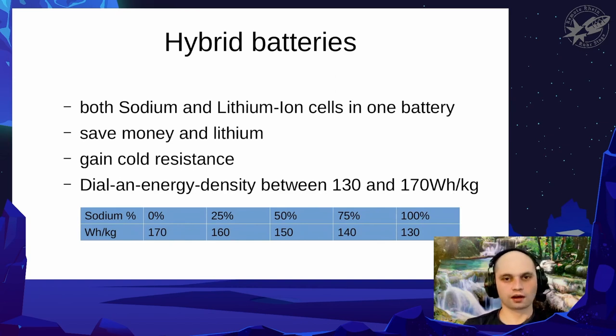And in terms of energy density, you can really choose what you want, and I've done it here with watt-hours per kilogram, but it works the same with watt-hours per liter, depending on whether your problem is getting small volume or small mass, whatever you want. And so if you choose 25% sodium, you can get a slight decrease in energy density. If you just give up 10 watt-hours per kilogram, so you go from 170 watt-hours per kilogram to 160, you can save 25% of the lithium in the battery pack. It's absolutely possible to save a lot of lithium that way, and especially when the lithium supply is tight, this can be very important.